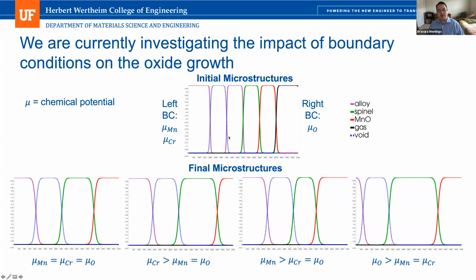So currently we're assuming all the different compositions are moving with the same kinetic rates until we get a better idea about the kinetics from the DFT. But we can look at just the impact of boundary conditions. So we have an initial microstructure where we have some metal, then we have a void, and then we have some more metal, and then we've got a thin spinel, a thin manganese oxide layer, and then our gas, where our oxide will grow into the gas region.